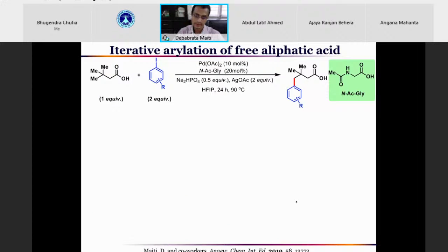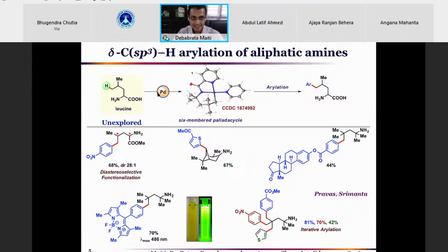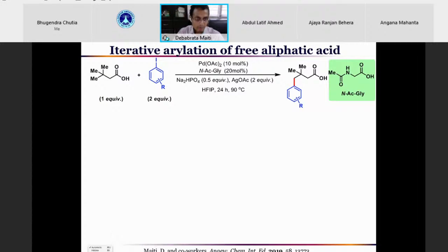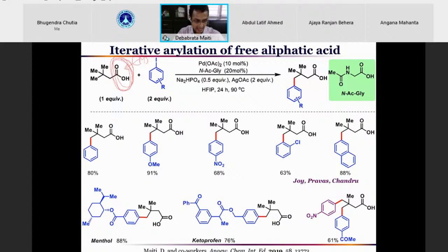One of the limitations is that we have to introduce a ligand. Usually, as you are seeing, we have to introduce a ligand like this pyridine carboxylic acid with the organic substrate. Now, can we do this reaction simply on the acid without introducing a directing group or ligand, by utilizing the acid as a directing group itself? This is a weakly coordinating ligand for the metal center. Can acid itself direct? Yes, it is possible, but of course not in every case. These are selective cases where we were able to show that acid can direct the functionalization. For example, in this case, arylation reaction can be done with acid. We can do one arylation, even two arylations. In all these cases, simple acid can do the reaction.